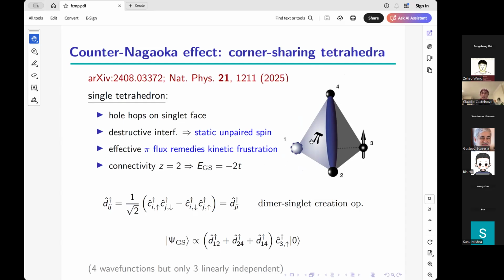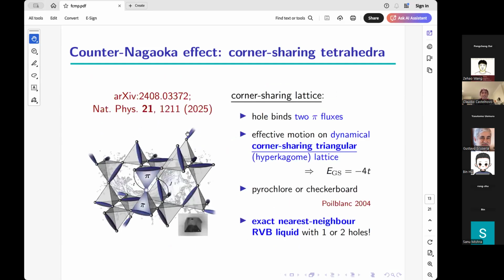Right? The hole is hopping on a ring. The ring has connectivity 2. The lowest energy is minus 2t, as you expect from a simple tight binding Hamiltonian. Of course, this looks beautifully elegant, simple, etc., but it's a single tetrahedron, and one would expect that it would fail as soon as you're trying to build a lattice from this elementary unit. And this is really the surprise of all of this physics, the fact that it absolutely doesn't.